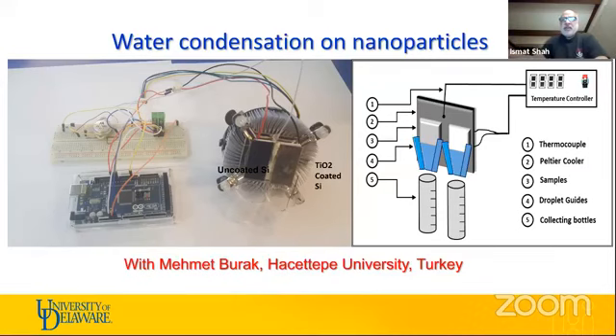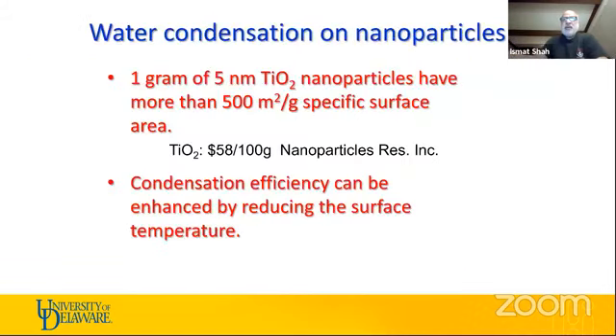Very simple project. And the beauty of that is that titanium dioxide is relatively cheap, $58 per 100 grams. But look at the surface area that you get. 1 gram of 5 nanometer titanium dioxide that is easily available has a surface area of 500 meters square per gram. 500 meters square per gram, right? So what does that mean?